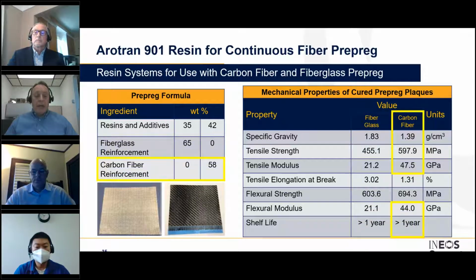Speaking of those carbon fiber panels, the carbon fiber panels exhibited high tensile and flexural modulus performance at a very attractive specific gravity. That's typical for continuous carbon fiber applications, of course. The carbon fiber also gave the expected enhancement to tensile and flexural strength versus the fiberglass panels. So it's easy to see how a near net shape preform with continuous fiber impregnated with the styrene-free resin could be used to create a lean and efficient manufacturing operation.